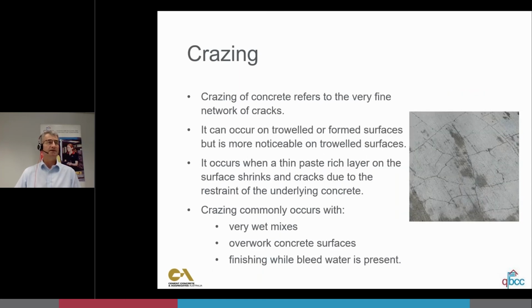Crazing is probably a little bit similar to plastic cracking, but it's more associated with a thin paste layer on the surface of the concrete. It can occur with wet mixes or overworking of the concrete surface or finishing while the bleed water is present. Again, if you force or work bleed water into the concrete, you're going to increase the water cement ratio at the surface. You'll make that surface paste weaker and more susceptible to cracking.